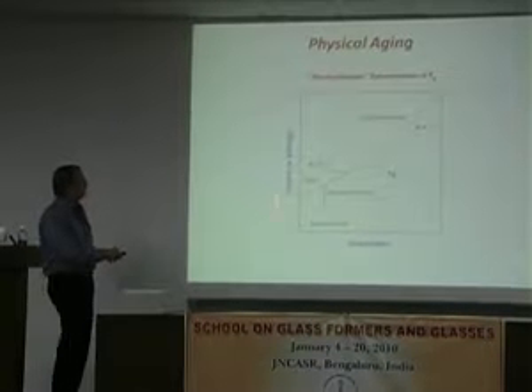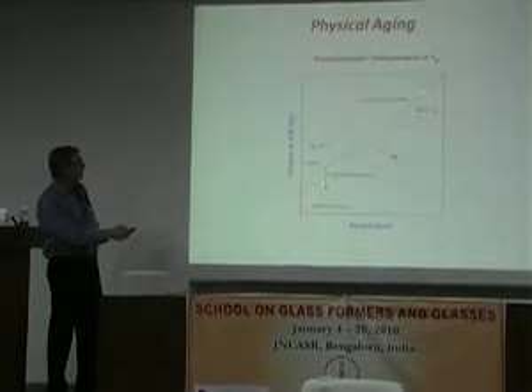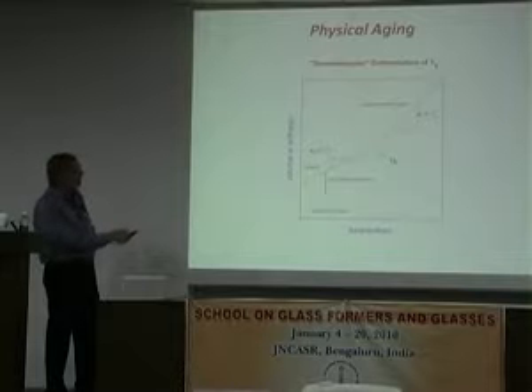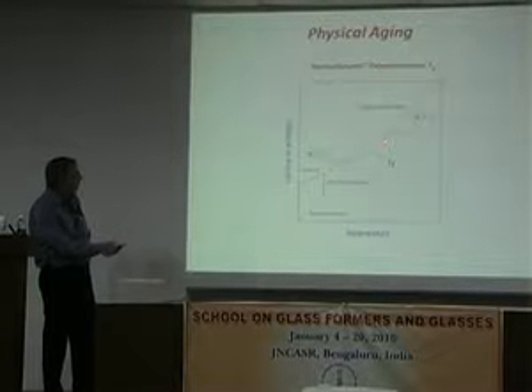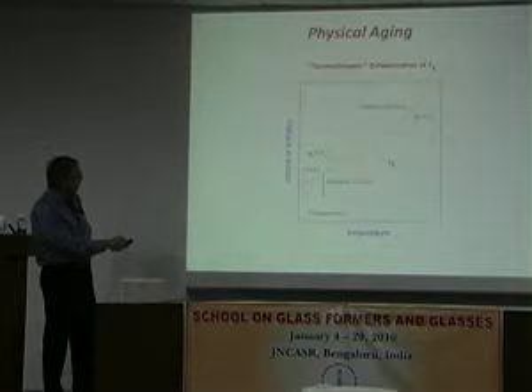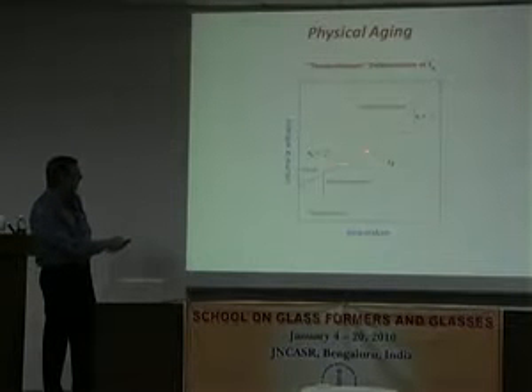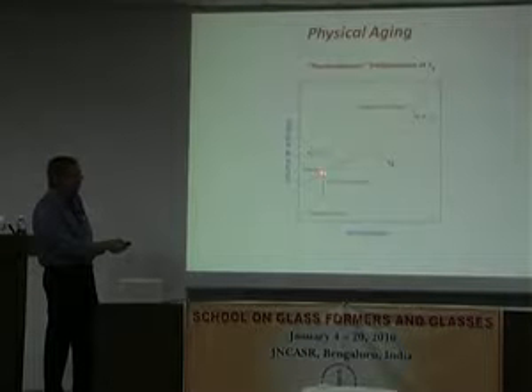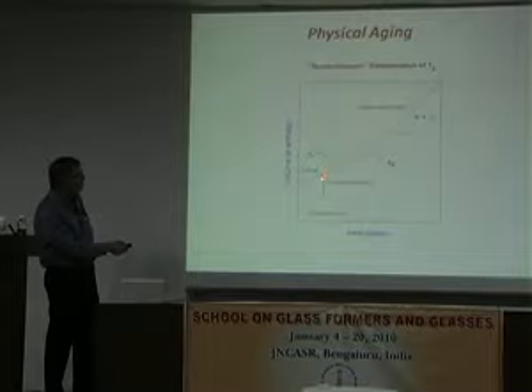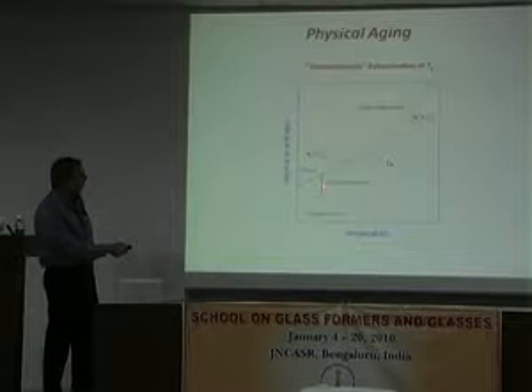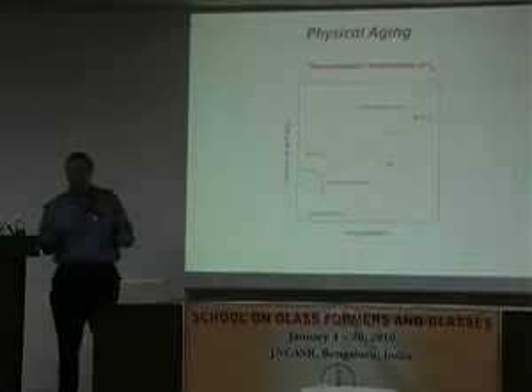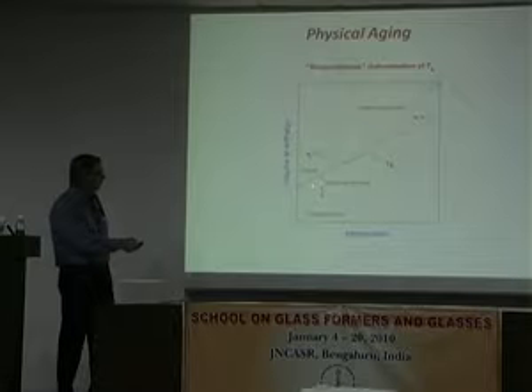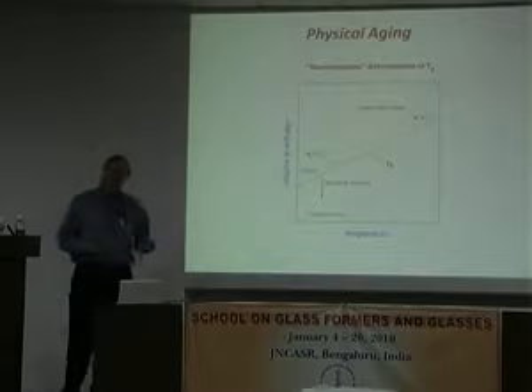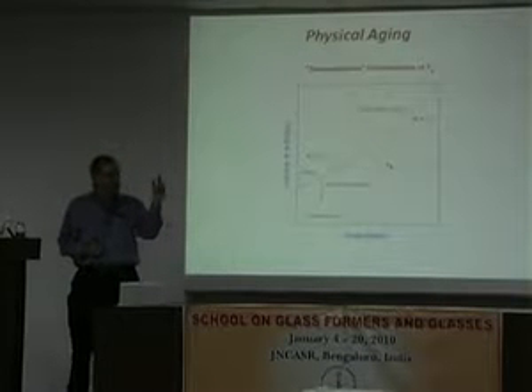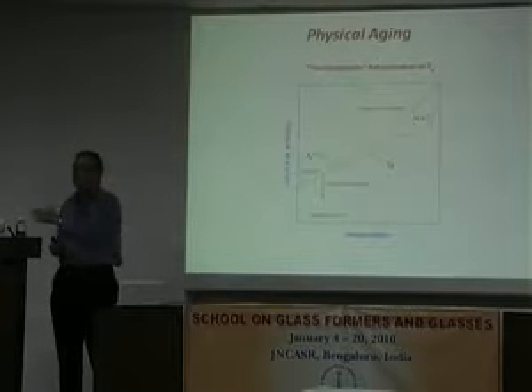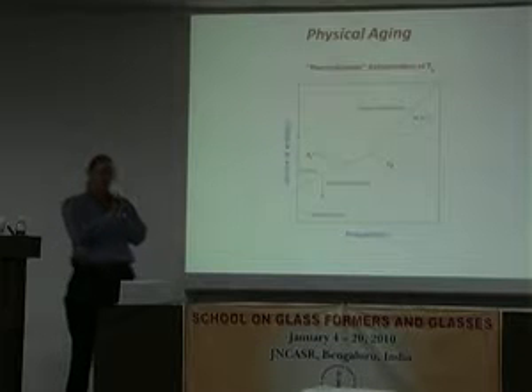So I'll remind you of our sort of default figure 1 here. As we come from a supercooled liquid, or in many cases for polymers, the equilibrium liquid state, as we cool, at some point we deviate from the equilibrium line, and that's what we call the glass transition. If we sit isothermally, and this is the most common aging experiment, as the structure recovers, what we want to do is try and understand, at each point along the way, what's the change in, say, the viscoelastic response, okay? And it's really important because what we're trying to do here is take a snapshot of what the instantaneous structure of the glass is doing to the mechanical properties. And that way we're using the mechanical properties as a probe of the structure.